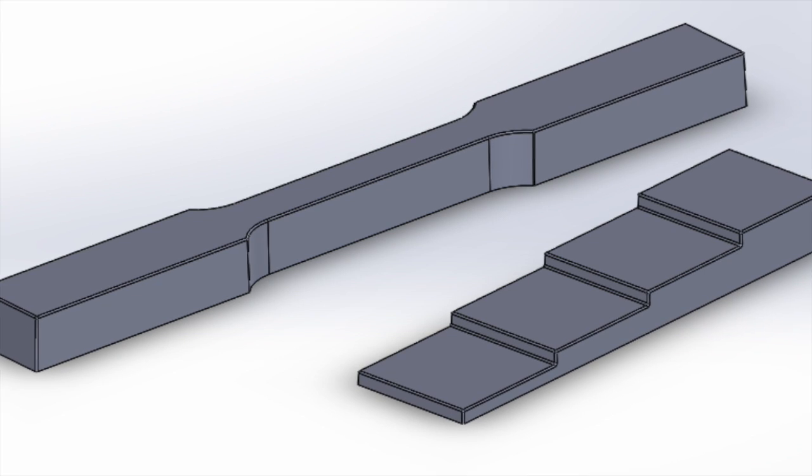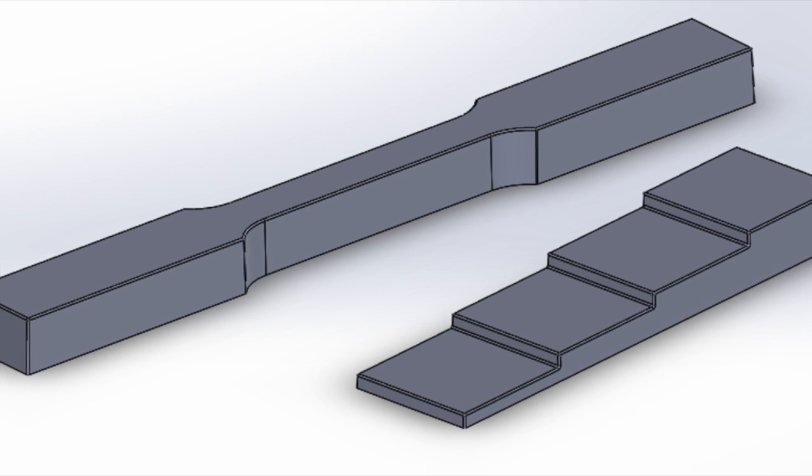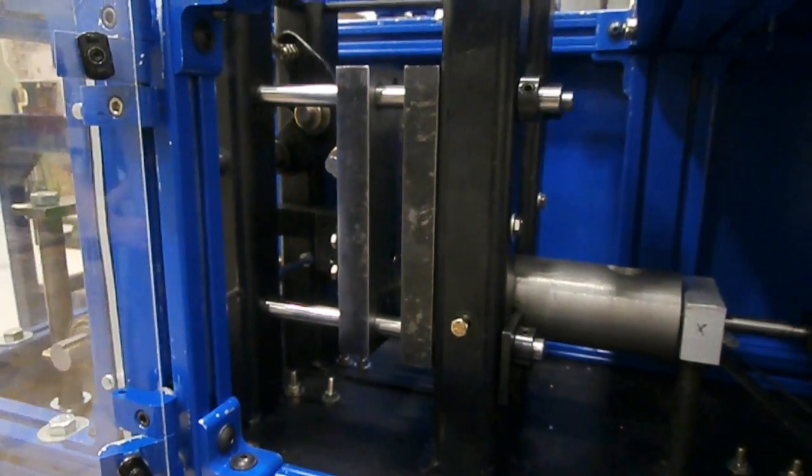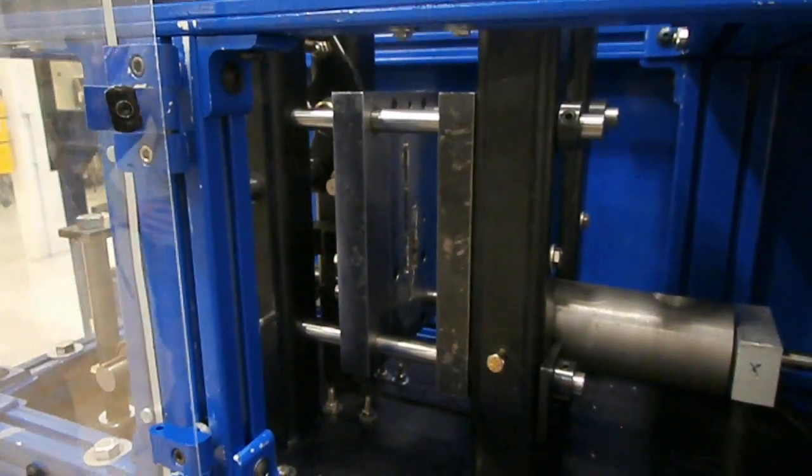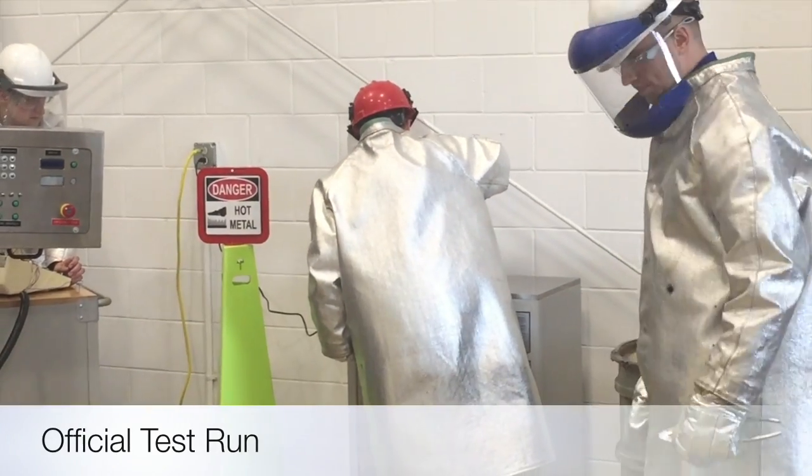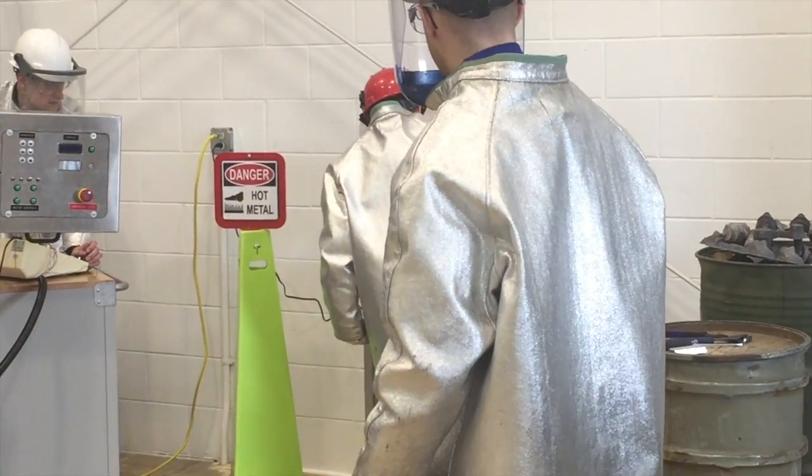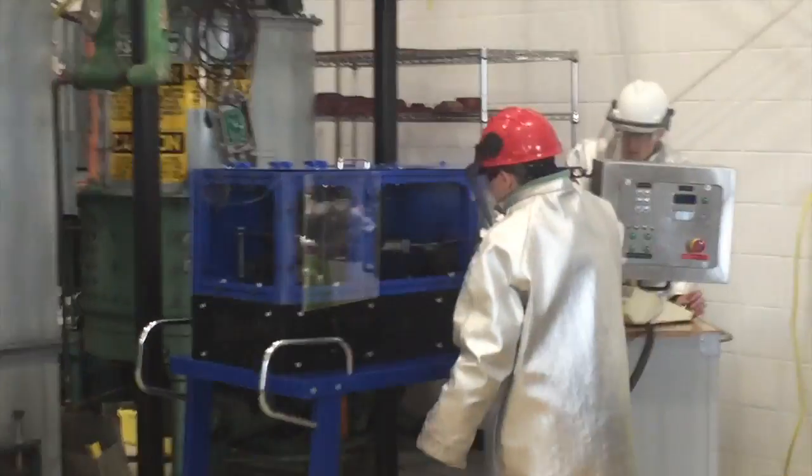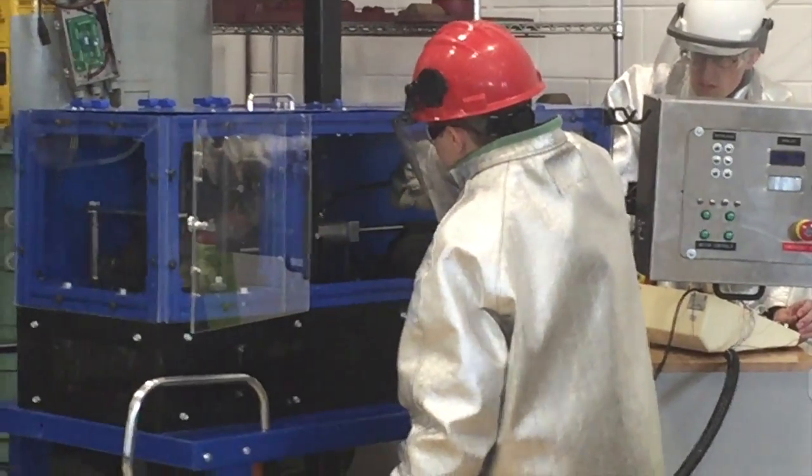The step block we designed is 0.05 inches thick. Once the part is casted and cools, the locking mechanism must be released and the die opened. In this demonstration, the tin solidified in the shot tube and bound the plunger and did not allow a part to be cast.